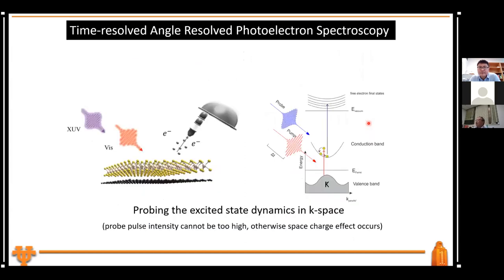Now, you will say, well, as I indicated, that is an indirect method, right? So now I'm going to give you a more direct method that is using time-resolved, angle-resolved photoelectron spectroscopy. It is a very complicated procedure, but the basic idea is you use a laser pump to excite a state into the conduction band, then use another probe to excite the state that you pumped into the conduction band, and then you detect them.